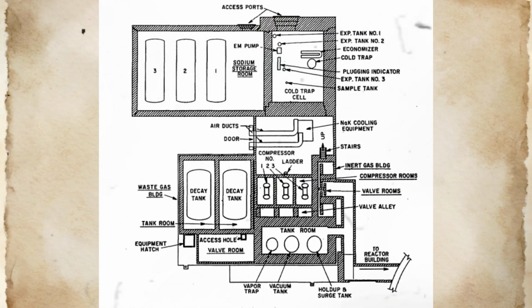The timeline of fuel damage progression was reconstructed through analysis of the fission product release signatures, detected in the reactor's cover gas and coolant systems. The isotopic composition and decay characteristics of released fission products provided information about when fuel damage began and how rapidly it progressed during the final hours before reactor shutdown. This forensic analysis indicated that significant fuel damage had been occurring for several hours before radiation detection systems provided clear indication of the problem to reactor operators.